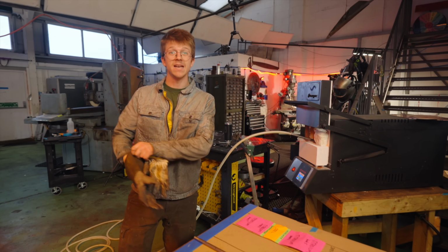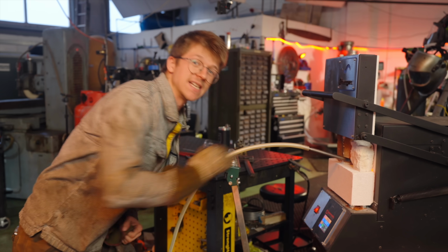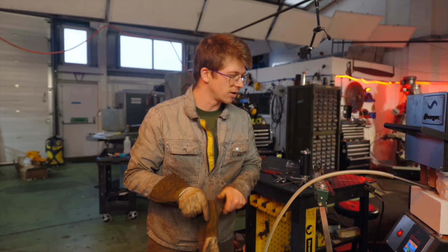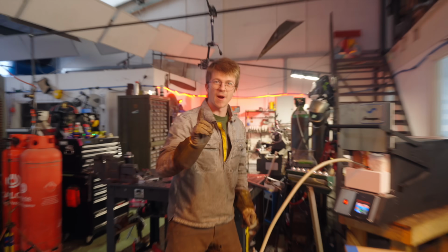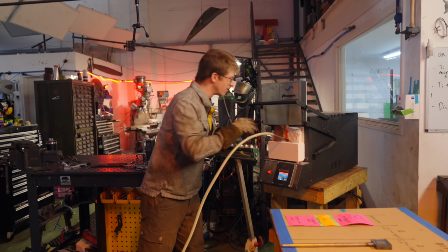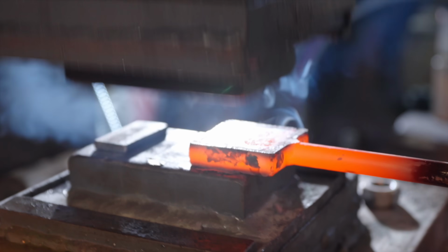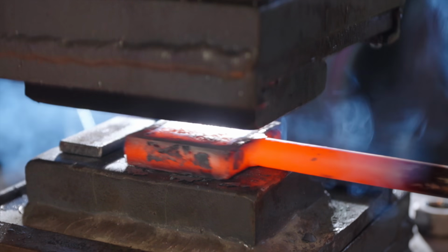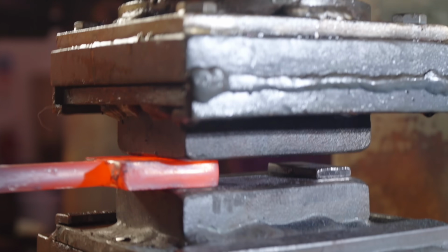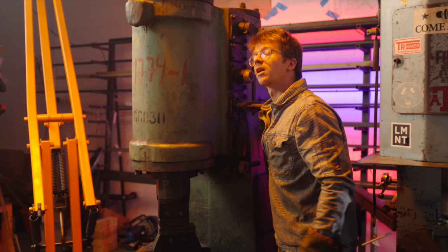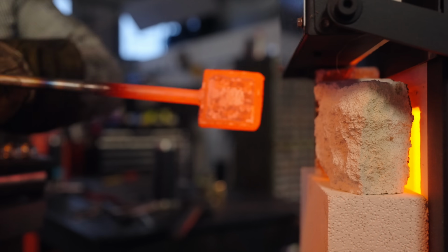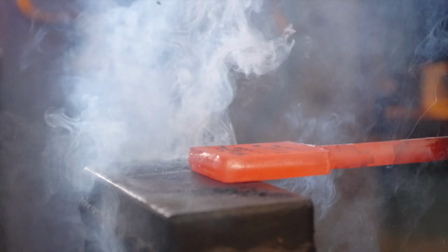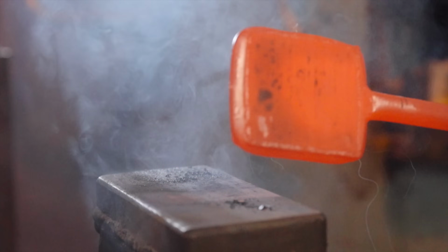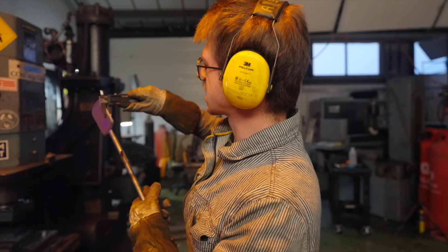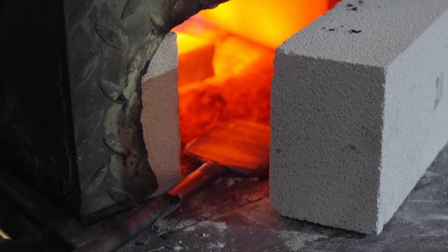It's been in the oven for 10 minutes and it's definitely up to temperature because it's an even color between the oven and the material. Turn on the hydraulic press. This is experiment 1, 0.1mm copper, here we go. It is so much less dramatic when it's not very hot. Second heat. And our third heat, we're going to bring it to size with the power hammer. Here we go. Put it down to 7.6 millimeters. We'll let them slowly cool here in the back of the forge.